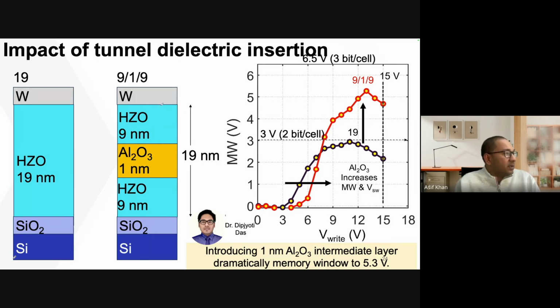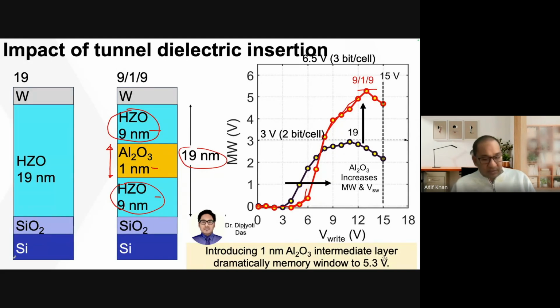Then Dr. Das came up with this interesting idea: how about we introduce a very thin layer of alumina and sandwich it between 2 hafnium zirconium oxide layers of 9 nanometers. Still, the total thickness is 19 nanometers because you have 9 nanometers, 1 nanometer, 9 nanometers. So 9 plus 9 plus 1, 19 nanometers. Total thickness remains the same. And very surprisingly, we saw in this red curve that as you increase the voltage, the memory window keeps on going up, and finally it reaches a value of 5.3 volts, which is almost double what we had previously got. So that was the first interesting discovery that Dr. Das made.